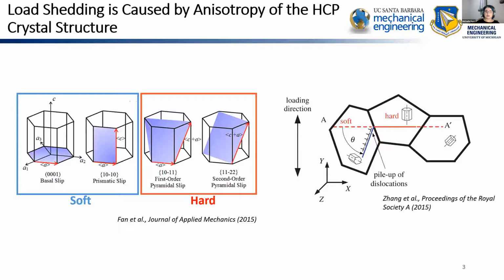And the worst case scenario is whenever you have one of those soft grains directly next to one of those hard grains under loading in your microstructure. So upon loading, your soft grain will have dislocations that form and then traverse through the material until they meet that hard-soft interface and create a pileup, wherein the soft grain will eventually stress relax, no longer be able to carry its load and shed its load onto the hard grain, creating a location of high stress that will often fracture via quasi-cleavage and create an ideal location for early crack nucleation.